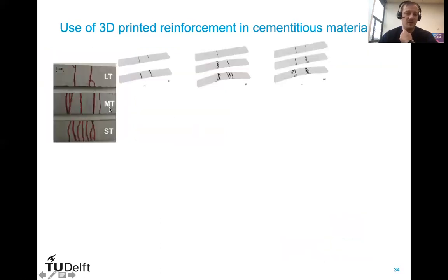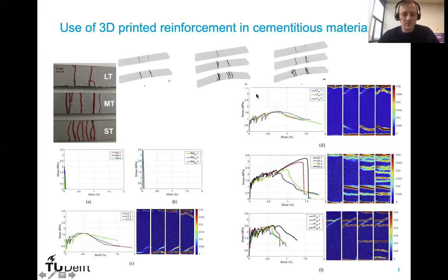So first, experimentally, we saw that with large triangles, we cannot really get multiple cracking and deflection hardening. But in 4-point bending, we can do that with mixed triangles. So we have an increased reinforcement density in the middle, sort of a functionally graded material, and with a small triangle. So if we increase the percentage of 3D printed reinforcement, we can get, of course, better behavior. And our simulations show that. So this is for the large triangles. For the mixed triangles, we have multiple cracks inside of the bending span, and for the small triangles as well.